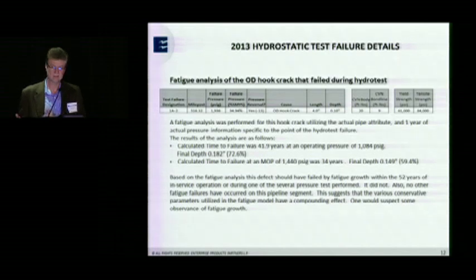Where it was located, it's about 30 miles downstream of a pump station. That was the highest pressure it saw. That would be about 42 years, with a final depth of 72% of the wall thickness. And then I reran and said, okay, well, let's run it until such time as it would fail at its MOP. And that was 34 years with a final depth of 60%.